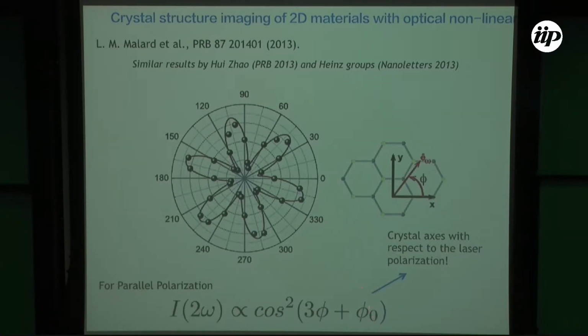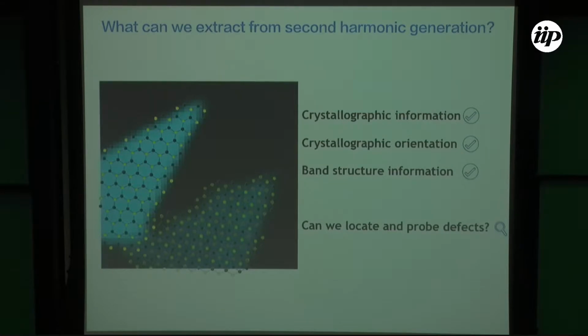And you have this phi naught. This phi naught is the angle between the maximum intensity of the second harmonic and the armchair direction. So basically, we can know where the armchair direction is aligned with respect to the input laser polarization. So we can know the crystallographic axis of the samples. So we can do something like this: you have the monolayer emission and the three-layer emission, and then we can directly determine the crystal orientation of these two flakes.